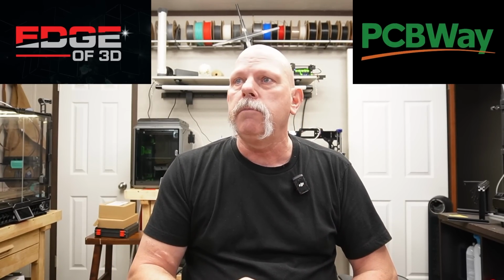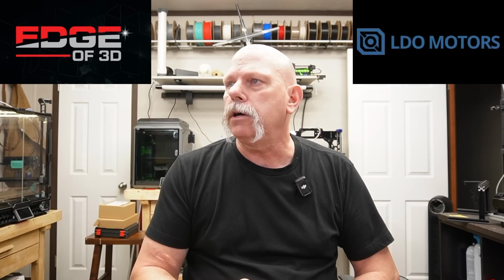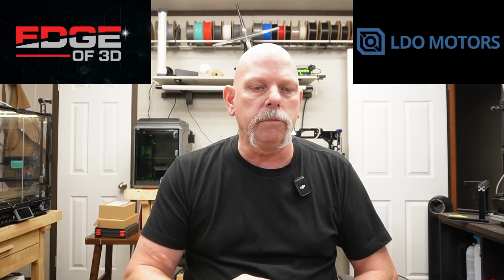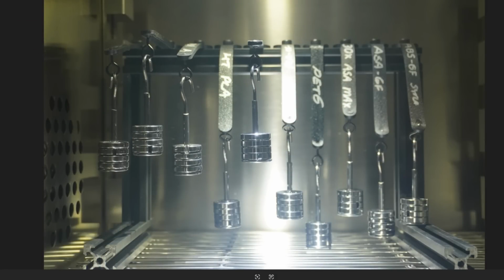And we grabbed the picture and put it over here on the other screen, and we'll switch to that right quick. And let me turn on the mouse cursor. Sorry, the lighting inside of the oven isn't all that great, but this is at 110 degrees Celsius. And you can see that, well, the ABS and the ASA, they've failed. The ASA Max has failed. The PETG has way failed.